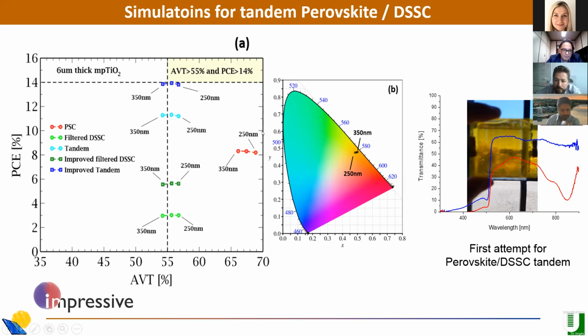So if we sum these two, then we can get a final tandem solar cell that has an efficiency close to 14% with 55% of transparency. So this is quite interesting, very critical, very difficult to achieve, but not impossible. So it's just part of an optimization. The strategy has been defined, but we need to optimize.